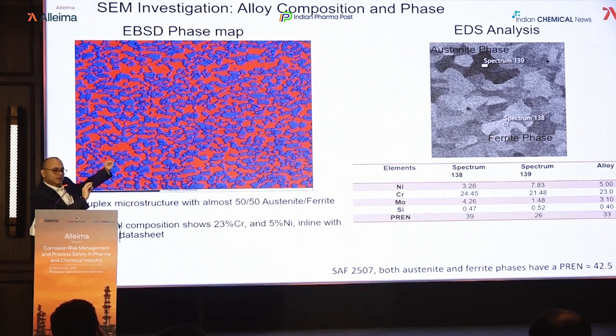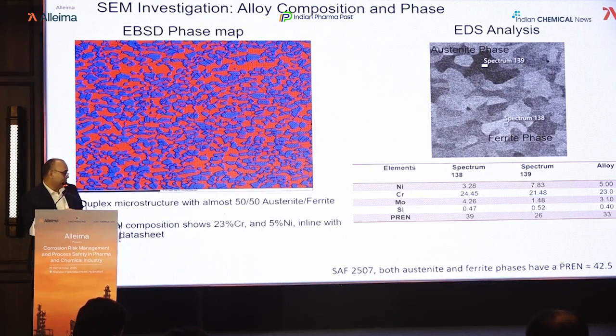You can have EDS analysis where you basically have information from the two phases, so 138, 139, and 139, if you see the chemistry, so that is having higher nickel, and chromium is less, moly is less, so you'll have lesser PREN. And on the other hand, 138, that is ferrite phase, so here you have less nickel, but high chrome, high moly, and you have high PREN number.